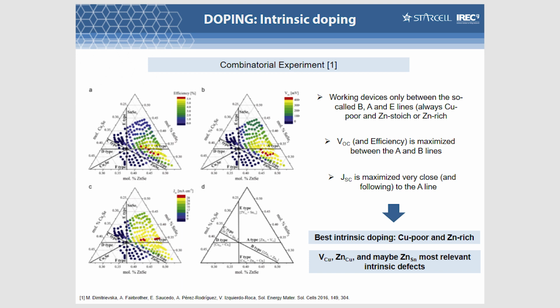What we can start to observe is that if we plot the efficiency, the VOC, the JSC as a function of the different types of kesterite that Susan has very well presented, we obtain maximum efficiency and VOC and JSC at different regions.